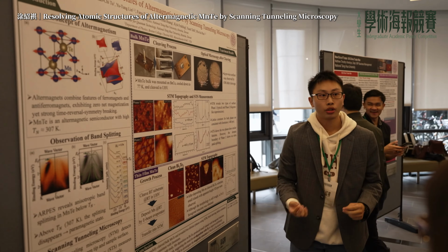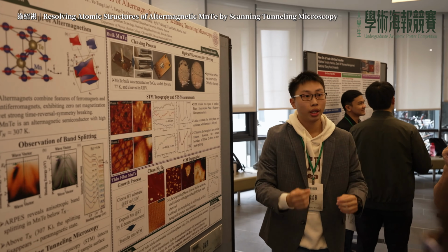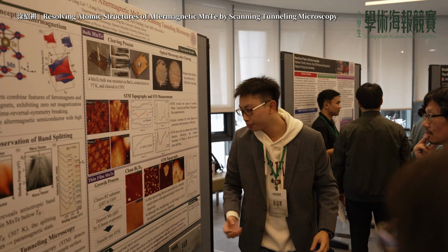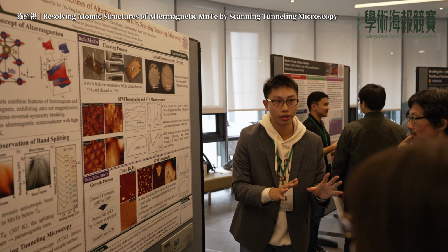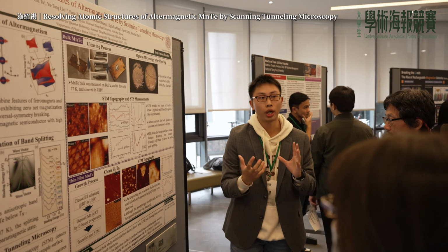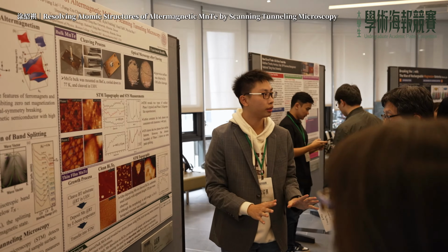This island shows a one-by-one hexagonal structure, indicating that Mn and Te are starting to assemble on the substrate, but the surface remains rough. So we will try co-deposition of Mn and Te to improve uniformity.